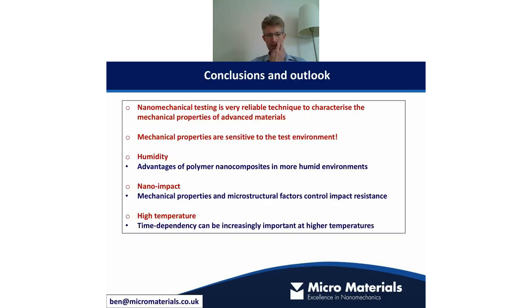So just to sum up, hopefully I've given you an idea about how to reinforce Andy's message about nanomechanical testing being a very reliable technique to characterize the mechanical properties of advanced materials, how we can look at that at very small scales and really get out properties that are sensitive to individual phases. It was described earlier about anisotropic materials in one of the questions. So we can pull out the different mechanical properties of the different crystallographic orientations, for example, just by indenting the surfaces of those different crystals.